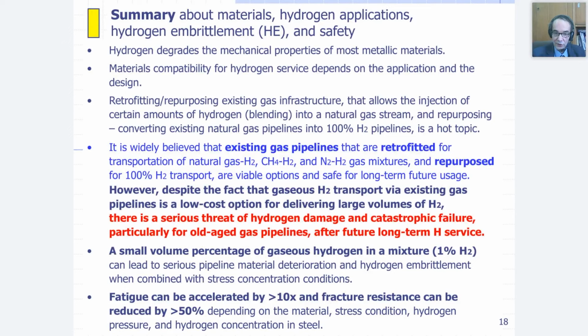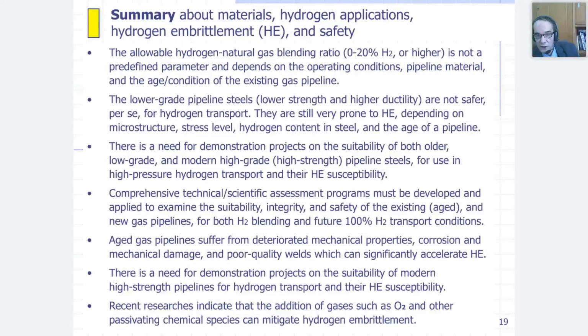A small volume percentage of gaseous hydrogen in the mixture, you can see only 1%, can lead to serious pipeline material degradation and hydrogen embrittlement, which produces the acceleration of fatigue by almost 10 times, while fracture resistance can be reduced by more than 50%, of course, depending on material, stress condition, hydrogen pressure, and hydrogen concentration in steel. So the allowable hydrogen natural gas blending ratio is not a predefined parameter and depends on the operating condition, on the pipeline material, and the most important, on the age and condition of the existing gas pipeline, which should be converted to the blending or 100% hydrogen transportation.